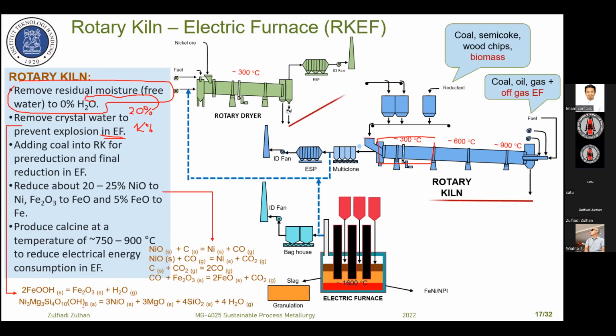And the crystal water, we can see the reaction here. The crystal water could be in the form of goethite. If you have goethite at roughly 500 to 600 degrees Celsius, we can dissociate the goethite into hematite and water. We can remove the crystal water in the goethite, so we get hematite. This is usually the case for limonite ore.